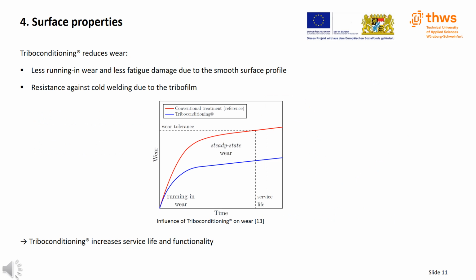The wear of a triboconditioned surface is also reduced. There is low running-in wear and less fatigue damage because the smooth surface profile contains hardly any prominent profile peaks and has good load-bearing capacity. Furthermore, the tribofilm offers a certain resistance to cold welding. In the illustration, the influence of triboconditioning on wear is to be seen. The amount of wear over time is shown. A conventionally treated reference part is shown in red and a triboconditioned part in blue.